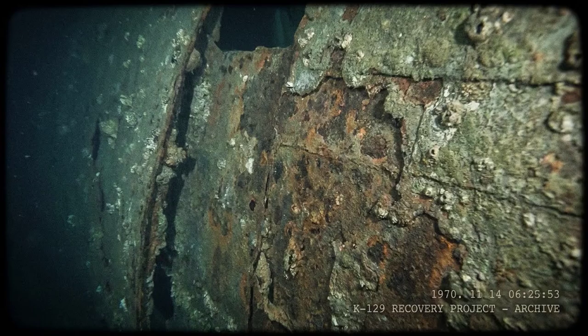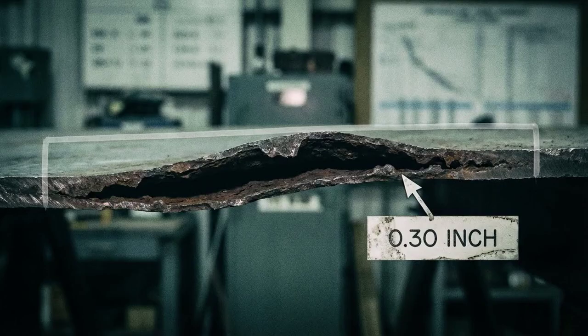The submarine hull has corroded for 6 years under 8,000 pounds per square inch of seawater pressure. The steel is embrittled, weakened by oxidation and stress fractures. Original hull thickness was ½ an inch. Now it is closer to 3/10 of an inch in places. The material has lost ductility. It will behave like glass under tension, fracturing along grain boundaries rather than bending.